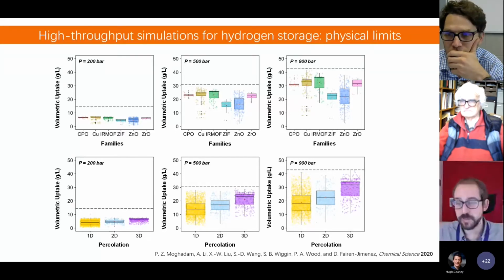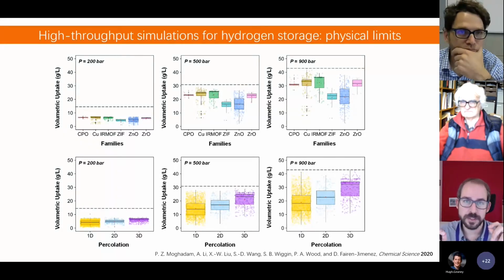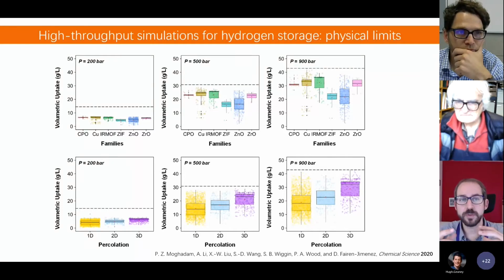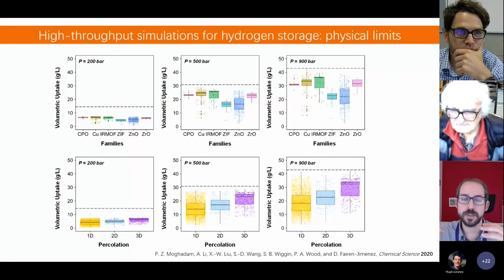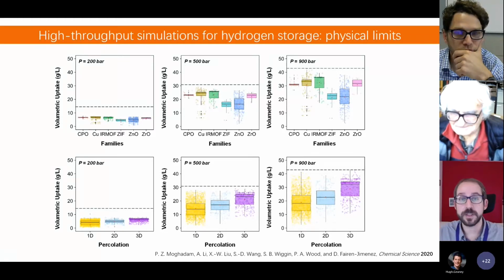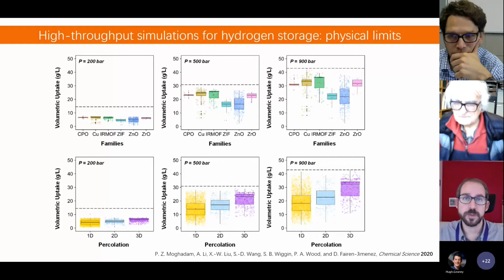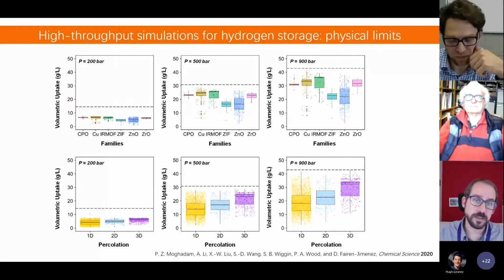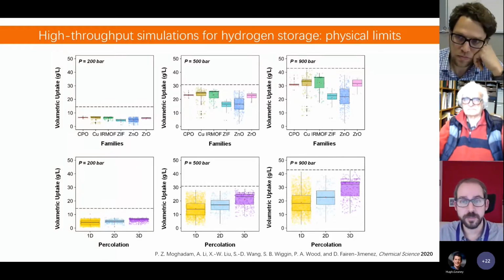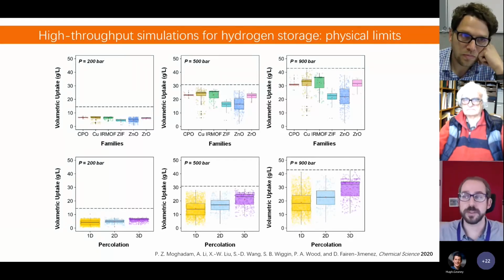That was for methane adsorption. It also depends on the different applications. In some cases, we have seen that some monolithic materials have extremely slow kinetics, and then we just need to engineer them in order to create some additional mesoporosity or something that will open the porosity, the connectivity, a little bit more, and this helps to improve the kinetics. Obviously, this will also have an impact on the density of the materials and the volumetric capacity, but there is a balance between all these different properties and possibilities.